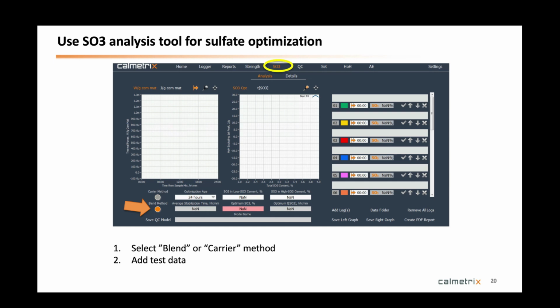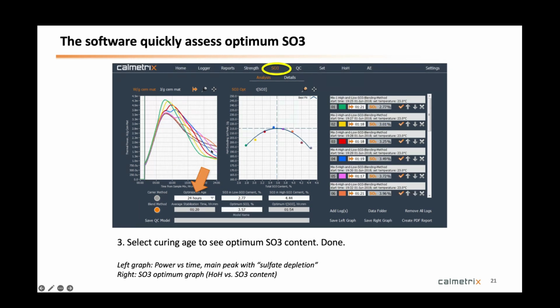You do a few samples with different levels of SO3 in them, and you get those curves there. It's actually all the same cement. The only thing that changes is just the quantity of sulfate in it, and you very quickly get an assessment of what the optimum would be. So the software spits out the optimum. It's really an easy to use tool compared to anything else that you would do.